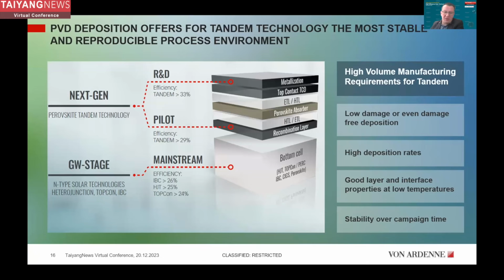For sure, for high volume manufacturing, there are a lot of requirements to be considered. Low damage, especially on top of the perovskite layer, is one big thing. But you also have to look at high deposition rates and good layer uniformity for the layer itself, but also for the interfaces to the layers on top and below, and especially at lower temperature when it comes to coatings after the perovskite layer. And you also have to look at the stability of these coatings over a long campaign time. So PVD coaters, for example, work 2, 3, 4 weeks in a row, and then you have to do the maintenance, and you have to achieve the same results in the first hour as well as after 3 or 4 weeks of this coating equipment.